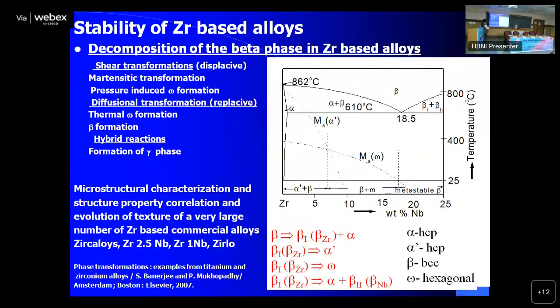So just to classify the transformations, he studied shear transformations involving martensite, pressure-induced omega, the diffusional transformation involving the thermal omega formation, beta formation, and he also studied the hybrid reactions, formation of the gamma phase. This is the gamma hydride phase, which is an undesirable phase. So in short, all possible transformations were studied by our group.